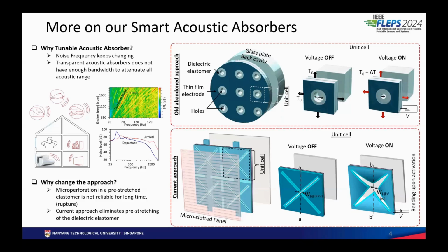To solve this problem, we worked on a micro-perforated panel absorber where the micro-perforated panel itself is made out of dielectric elastomers. So this is a dielectric elastomer actuator with micro-perforations. Upon activation of the dielectric elastomer, the perforation size can be reduced. By changing the size of the micro perforations, you can tune the peak absorption frequency of this kind of acoustic absorber. But the problem is, imagine a stressed polymer with numerous holes. Eventually, it's going to rupture, right? So the reliability of this kind of smart acoustic absorber is not really good.